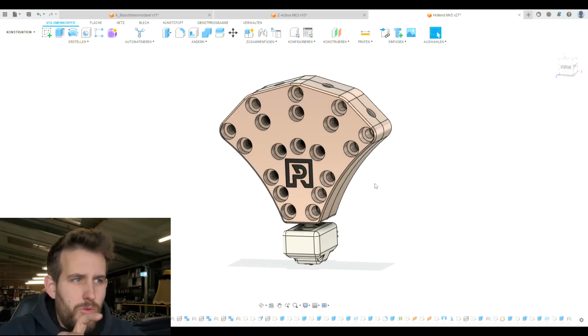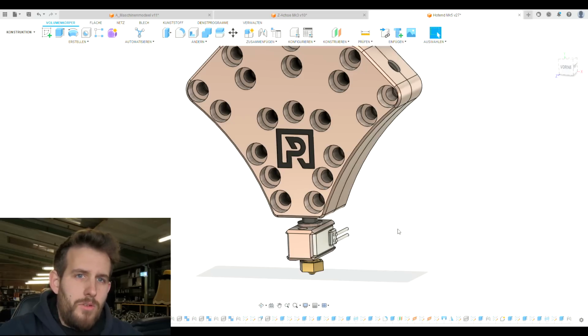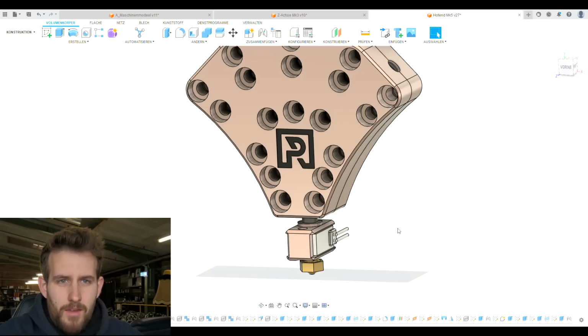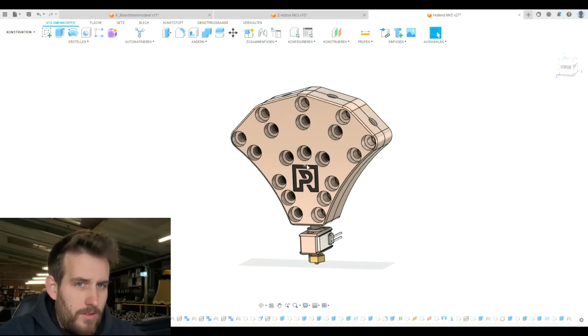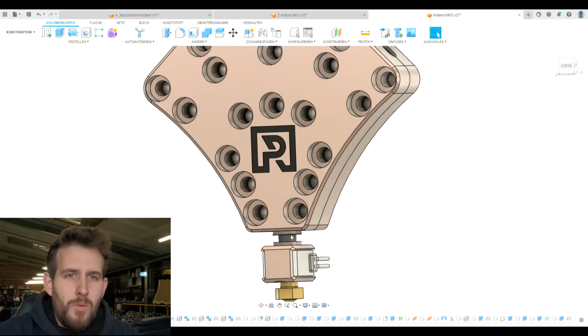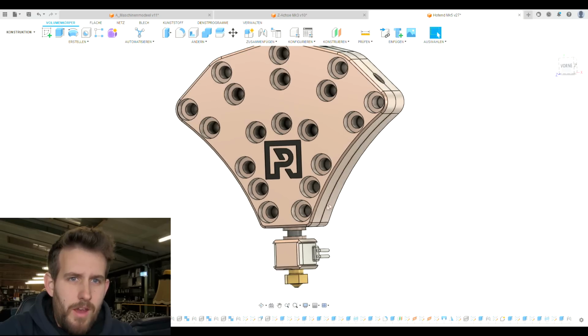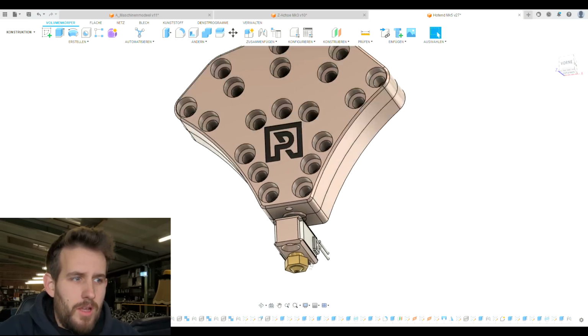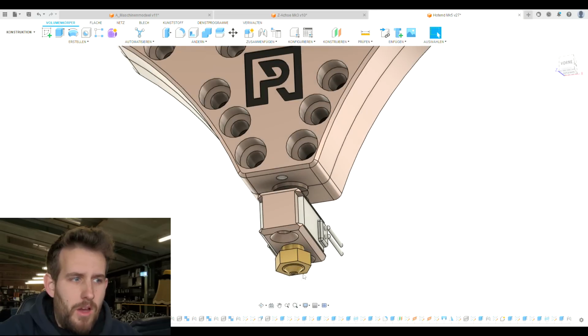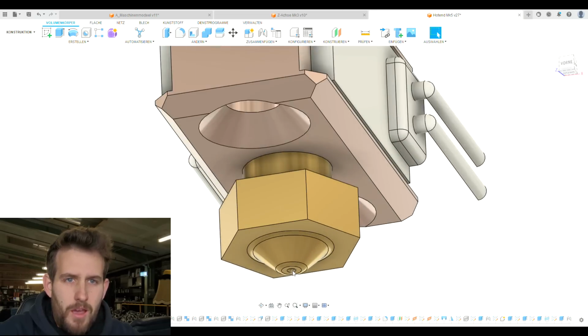We actually do have two heating zones. The upper part will be the one where filament comes in and will be heated as quickly as possible. That is its main job. And we can control these two zones pretty much independently, and they have their own control loop. As I said, this is going to dump as much heat as possible into the filament. At the exit down here, we want to have a set temperature and have the filament at a very low viscosity to cause very little back pressure in the system, because pressure is what actually is going to limit the performance of the Hotend and what actually is coming out of the nozzle here.